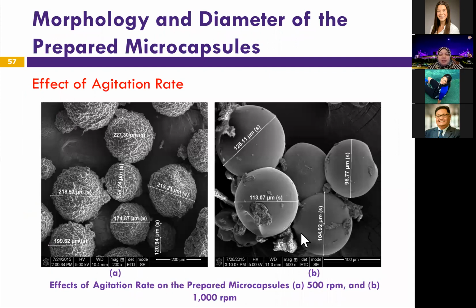Okay, this picture shows an SEM picture of the microcapsules that we developed, and we are able to control the shell thickness, the diameter, the morphology by changing the parameters of the process with which we're creating the microcapsules, like the agitation rate.